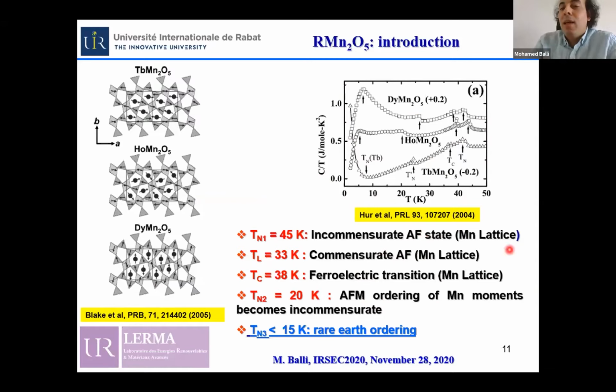Consequently, in these materials, an incommensurate antiferromagnetic state involving the manganese sublattice occurs at a temperature of 45 Kelvin. This incommensurate antiferromagnetic state gives rise to a ferroelectric order in these materials at around 38 Kelvin.